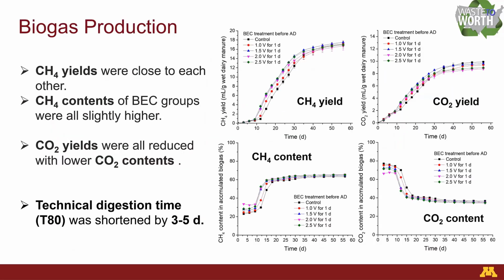So then we look at the biogas production. Because it's not simultaneous, the improvement in the biogas generation is limited also. The methane yields from all the groups are similar to each other, while the carbon dioxide yields were a little bit lower because of reduced carbon dioxide contents. And more importantly is the technical digestion time, T80, which means the time required to produce 80% of the maximum methane yields. This T80 was reduced by 3 to 5 days in all of the groups, which means for the BEC treated manure, the AD process was accelerated or the efficiency is improved.